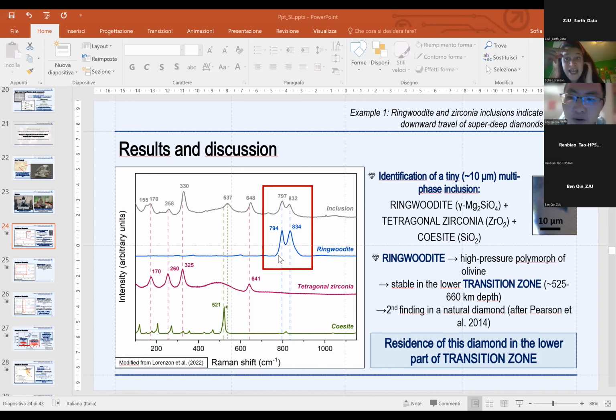But tetragonal zirconia is probably a back-transform product with respect to orthorhombic zirconia, and we cannot know how this influences the position of the Raman peak. And finally, about the coesite, yes, we know very well that our coesite peak is broader and is also shifted to a very high Raman shift with respect to the Raman spectrum of the standard coesite.